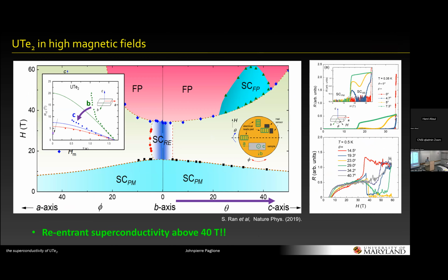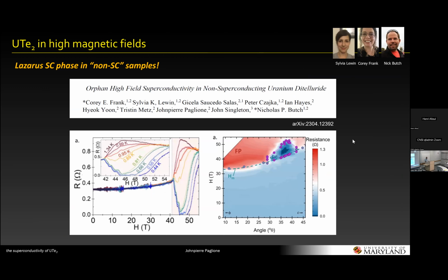And this has been studied by several groups now, confirmed, and so on. And in fact, in the latest, Nick's group has studied this in non-superconducting samples, and it's still there. It's still superconducting at 40 Tesla, even though you have no superconductivity at zero field. So that's quite unusual, unprecedented. And what that means is the next problem to solve: do they have the same TC, these two different superconducting phases, at the high field regime?